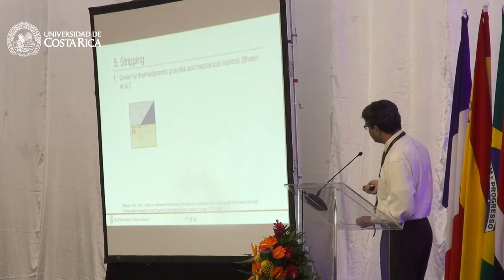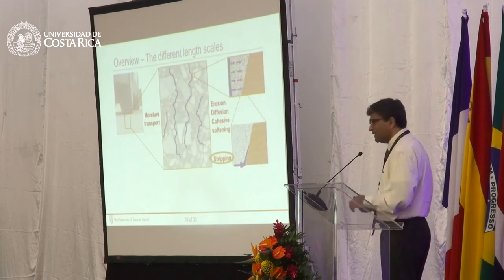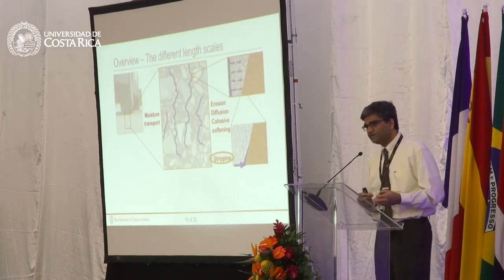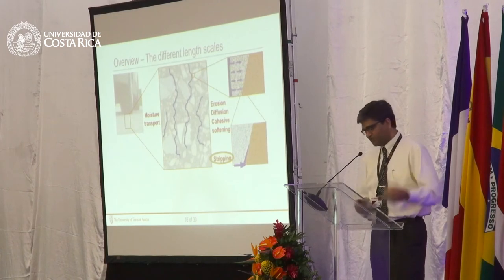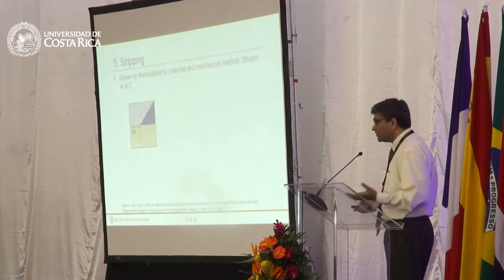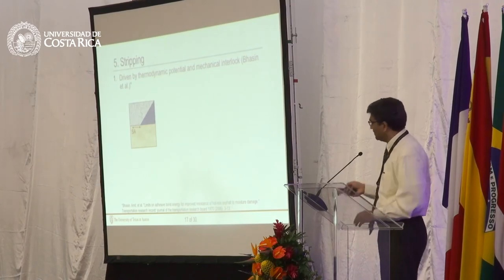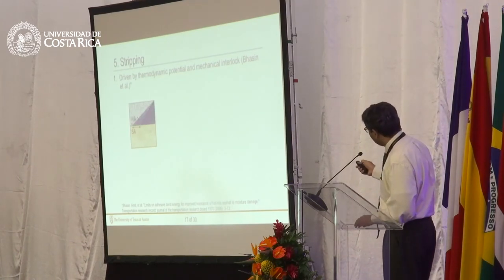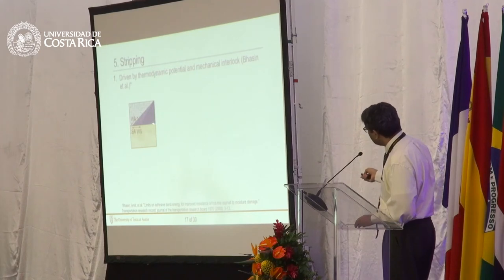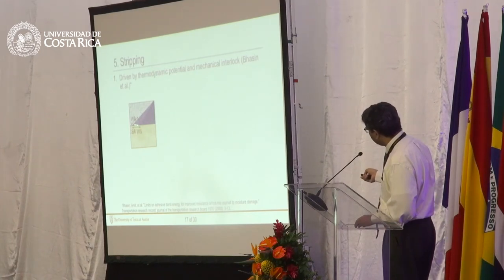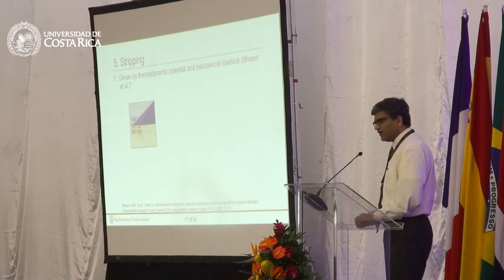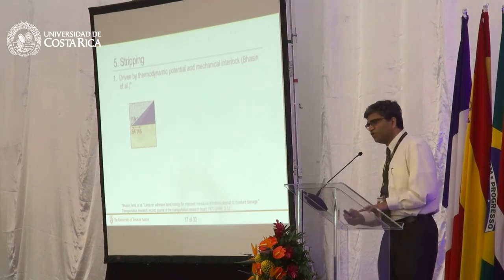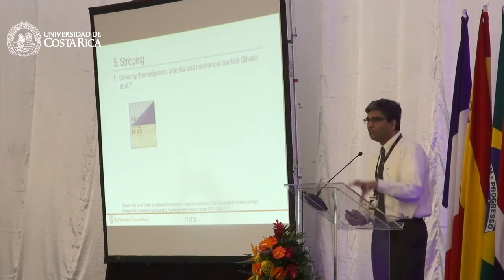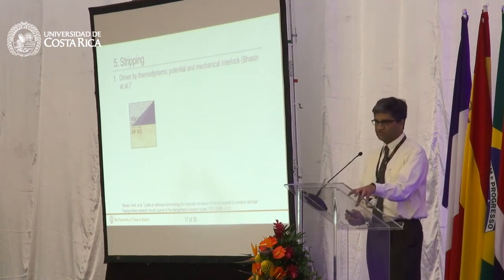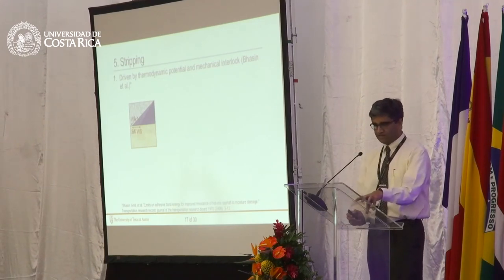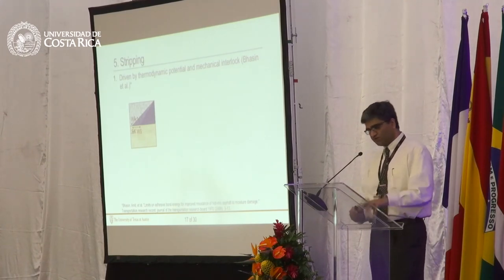Stripping, the last piece of the puzzle, is once moisture gets to the interface, it strips the binder from the aggregate surface and the aggregate breaks loose and pops out. So this is a thermodynamic driven process, meaning once you have an interface like this, where you have water sitting at the interface, the water gets between the aggregate and the asphalt binder, separates it, and creates a new interface. Why does this happen? Because water is highly polar, it prefers the mineral surface more than the binder prefers the mineral surface. It's just a competition between the binder and the aggregate surface versus water and the aggregate surface.